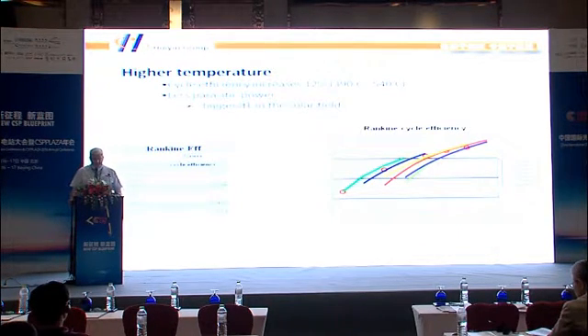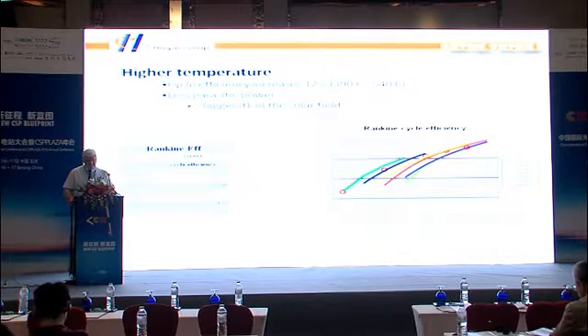And here we can see, if we look at just the cycle we had before, if we would take it to oil, we have a cycle efficiency of 37.7%. If we can take it to 550 degrees, we are at 42.4%. So this is a big increase in cycle efficiency.